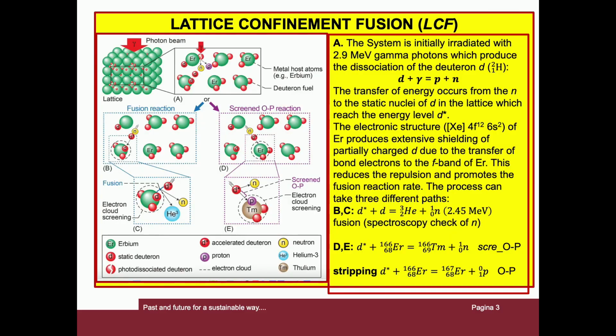The system is initially irradiated with 2.9 megaelectronvolt gamma photons, which produce the dissociation of deuteron into protons and neutrons. The energy transfer is from the neutrons to the static deuterium nuclei in the lattice, which are brought to an excited level, D star. The electronic structure of erbium produces extensive shielding of the partially charged deuterium nuclei due to transfer of binding electrons to the f-band of erbium. This reduces the repulsion and promotes the fusion reaction rate. The process can take three different paths.